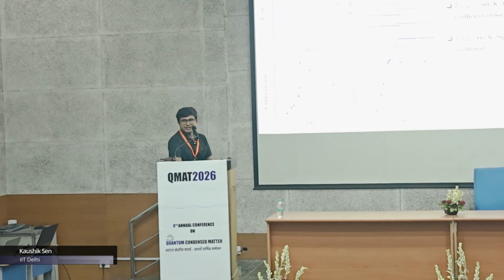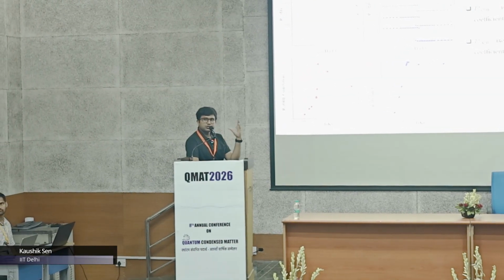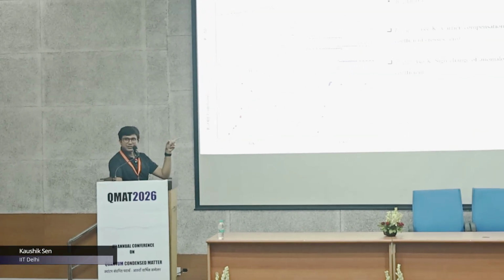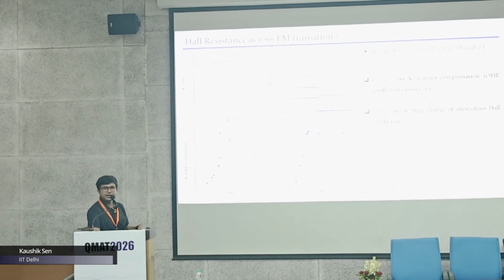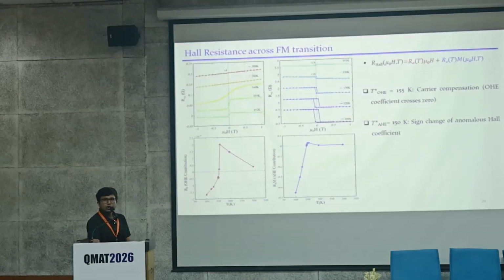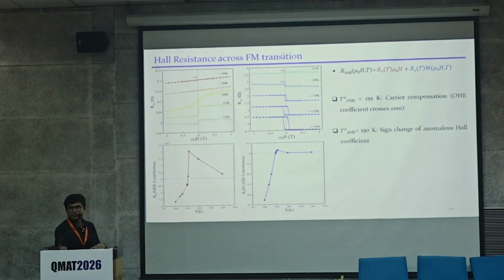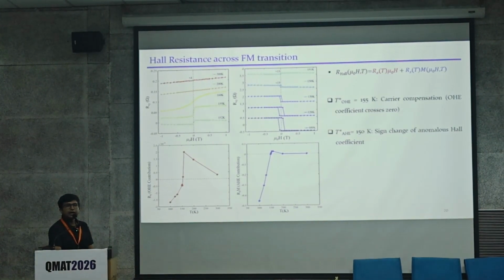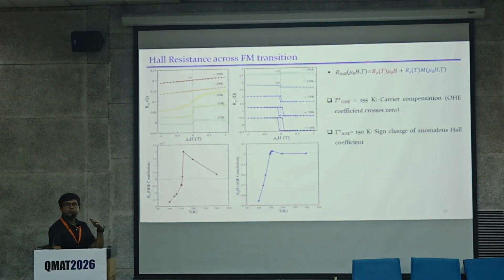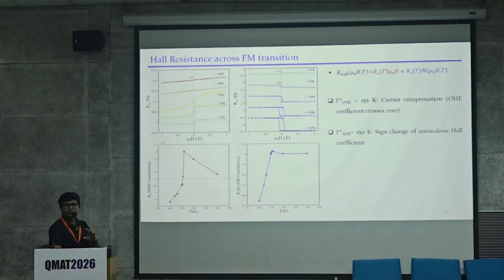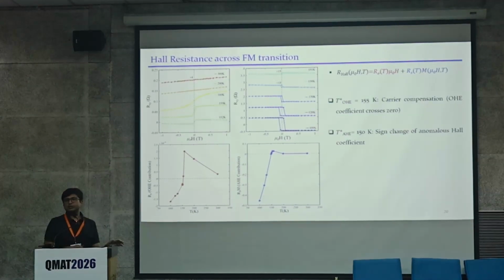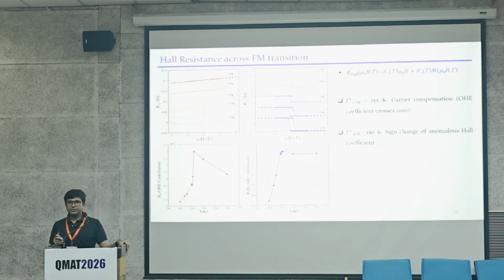Yeah, honestly, we did not do that. The reason is very simple. Look at our magnetic field. It's only 1 Tesla. And the topological signature not only from the anomalous Hall effect, you should do with the magnetoresistance as well, right, where the linear part is there. And it is not advisable if the field region is very low, like 1 Tesla. If it is a large field, then definitely you should do. Okay. And there are experiments that measured up to 14 Tesla, 15 Tesla, and they found there is a Weyl point, and that gives rise to large linear magnetoresistance. Okay, thank you.